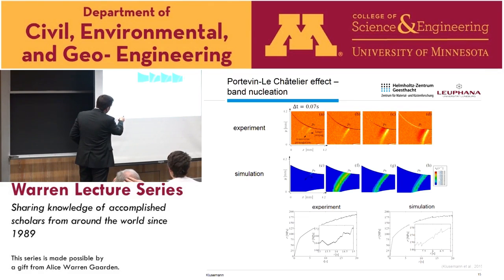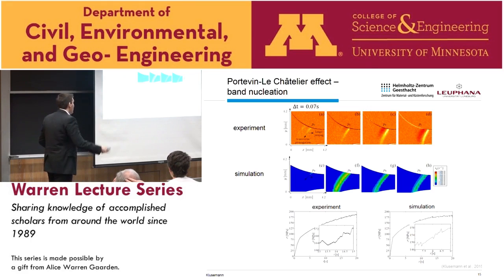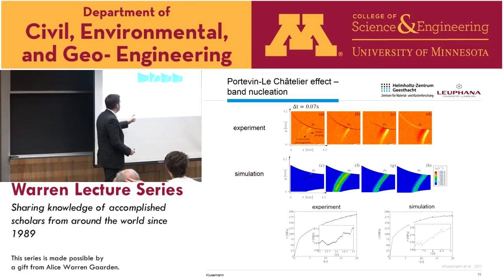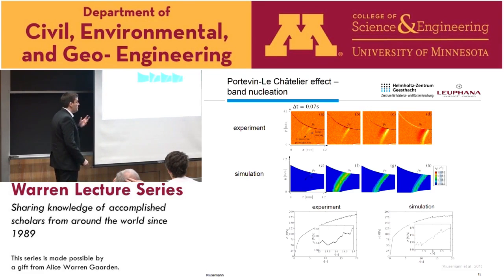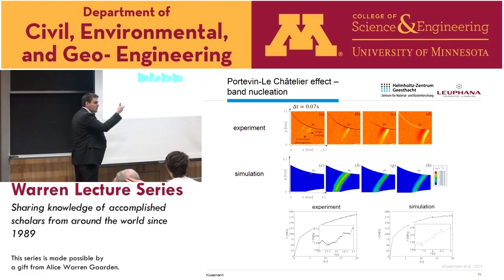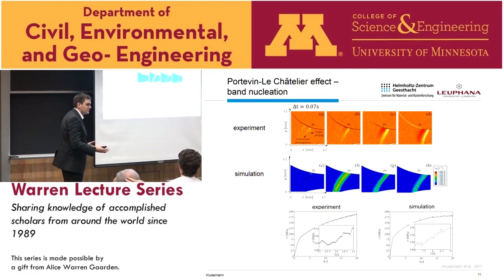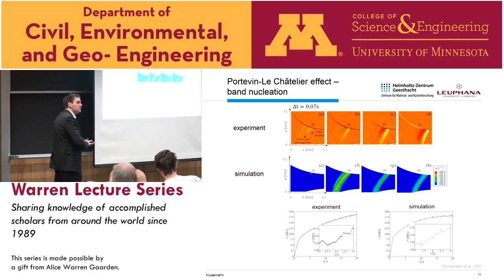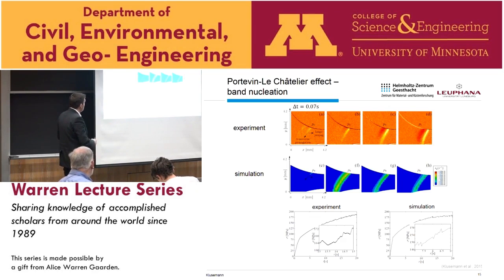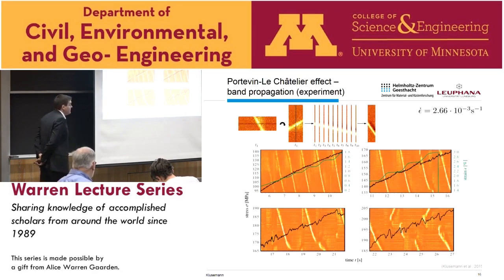Here it was a bit stronger, but here we also saw a starting point, and then the middle point was already shifted a bit, and then it continues, of course, to propagate. And we could then investigate the stress-strain level, and the starting point of the nucleation was mainly attributed to a large drop in the stresses. When the PLC band starts, the stress drops strongly, and then starts to increase continuously.